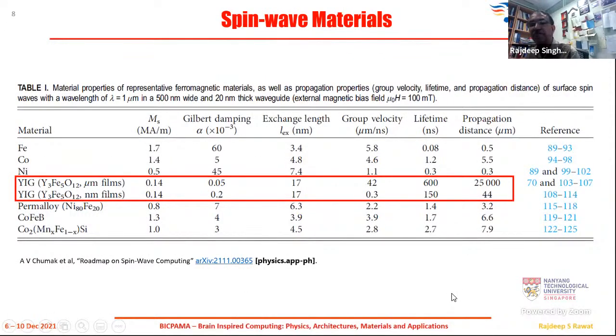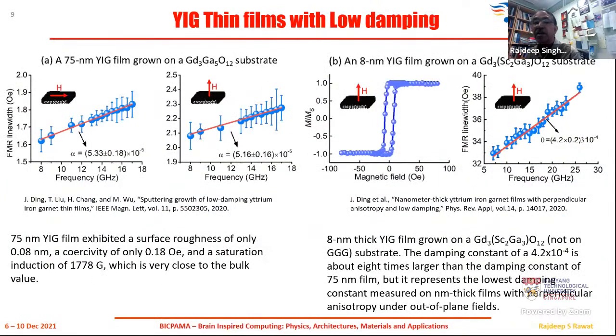So this is a table which shows several different properties. If you look at the last column, you can see that the propagation distance for YIG, if it is a micrometer thick film, is of the order of 25 millimeter. While for a material like permalloy, which is another hot material, if you want to go for a conducting ferromagnet for spin wave generation, the propagation distance is less than that. So the lifetime of spin wave survival is also longer. So if you carefully study this table, YIG indeed is one of the good materials that one can work on. Of course, the criticism will be that it is not CMOS compatible, and the growth conditions are also not very favorable.